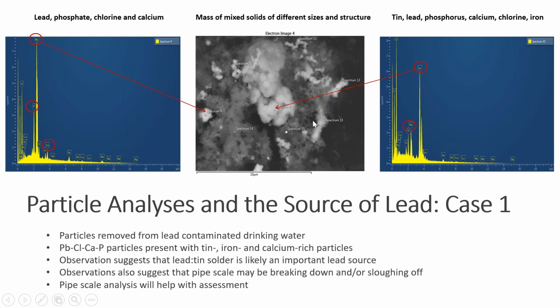And so if we look at different areas, what we have here are EDS patterns, if you haven't seen these, associated with areas that I've got the arrows pointed to. And so what we're seeing here is that lead particles are present in this mix of stuff, this mix of matrix, and these particles consist of lead, chloride, calcium, and phosphorus. On the other hand, they're mixed in with these other particles.